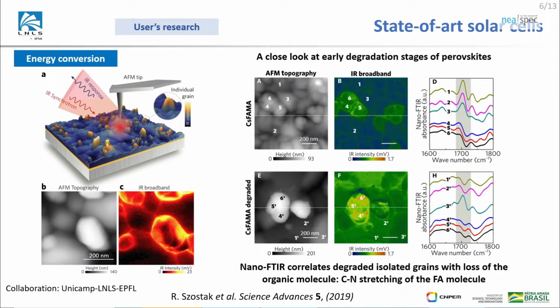And then we investigated the spectral response of those individual grains, and we could see that the band related to the CN stretch in this formamidinium molecule is actually changing, following this contrast. So as you can see here, this is a film that was naturally exposed to the environment, and we could see these bright spots here.